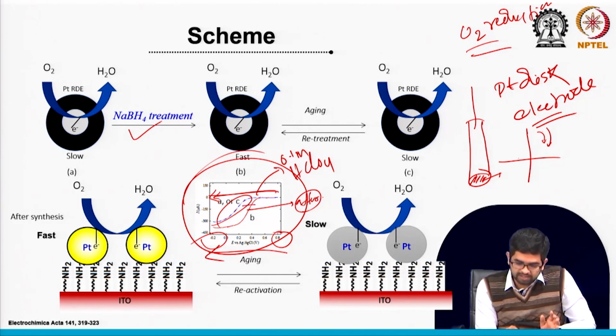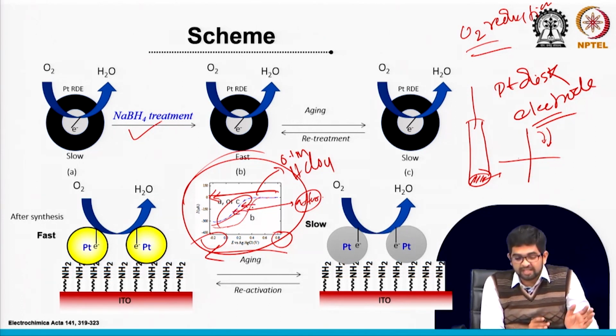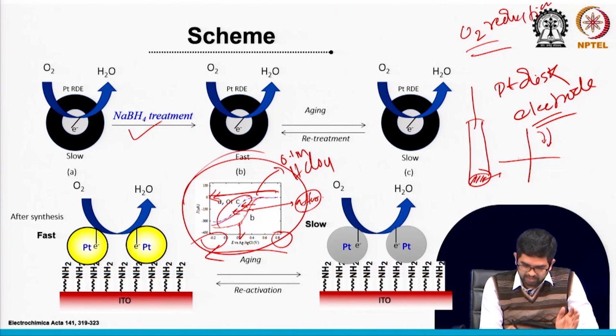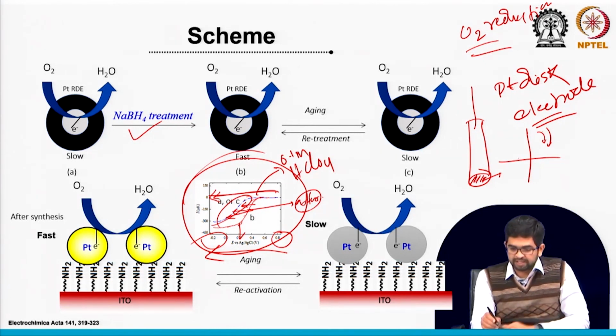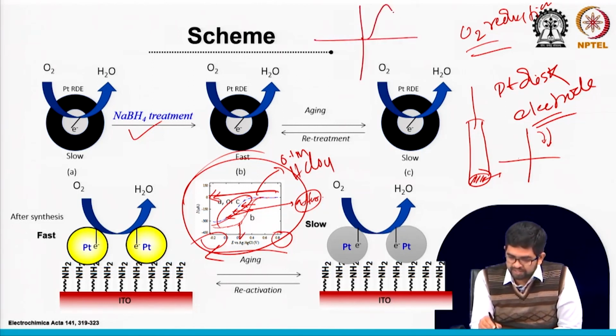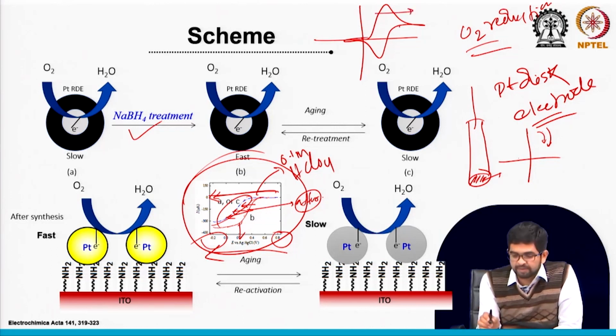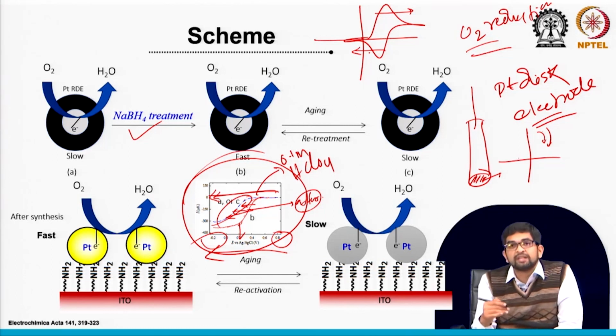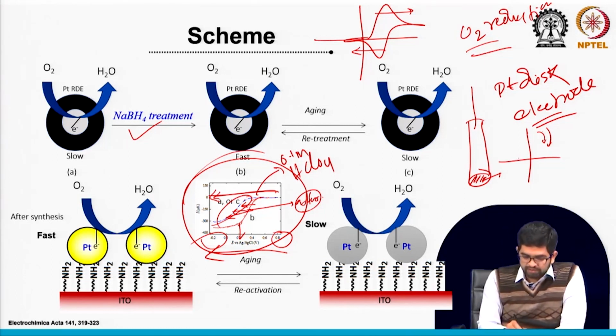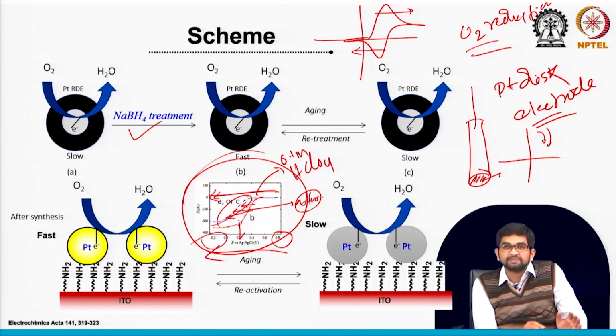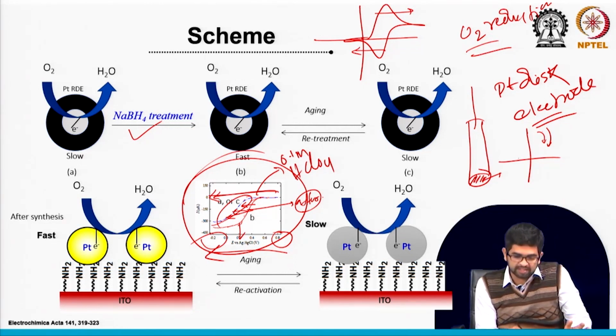You can see the deactivation here. The oxygen reduction is highest in the red one, but in this case it is actually shifted towards the left after the aging. So, we can say that this electrode actually deactivated after the aging. I can show you again: if the oxidation peak shifted towards the right, then we can say that the surface is deactivating, and if the reduction peak shifted towards the left, then we can say the surface is slowly becoming deactivated. You can see the reduction peak for the oxygen case is shifted after the aging. So, we can say the surface is actually deactivating.